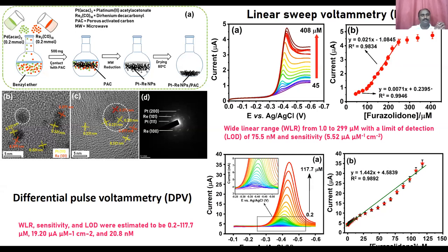And mixed together with the porous activated carbon and microwave reduction, the rhenium and the platinum are reduced to form the platinum rhenium nanoparticle, and finally dried at 80 degrees centigrade, we get this composite. So this composite is used for characterization by TEM image to find out whether it's a platinum and whether it's a rhenium nanoparticle.